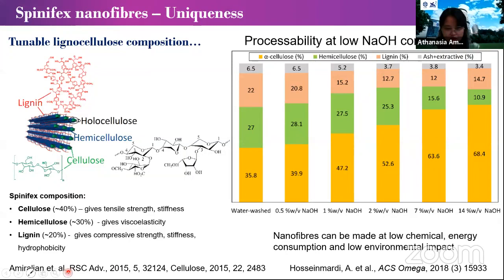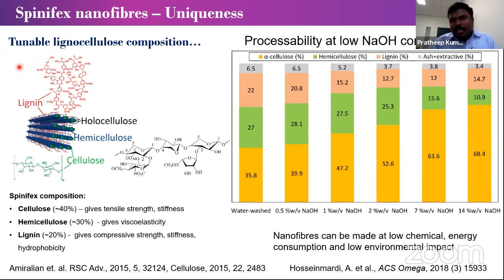And the uniqueness of any non-wood cellulose is that we can tune the composition, like the lignin and hemicellulose. You can see here the hemicellulose composition has been tuned and also the lignin. It depends on how we treat and how much concentration of chemicals we use. We can tune this composition because lignin is a more aromatic polymer, which, if coated on the surface, provides more hydrophobicity. Or you can tune the hydrophilicity of nanofibers. Okay, so that's the uniqueness of any non-wood nanofiber.